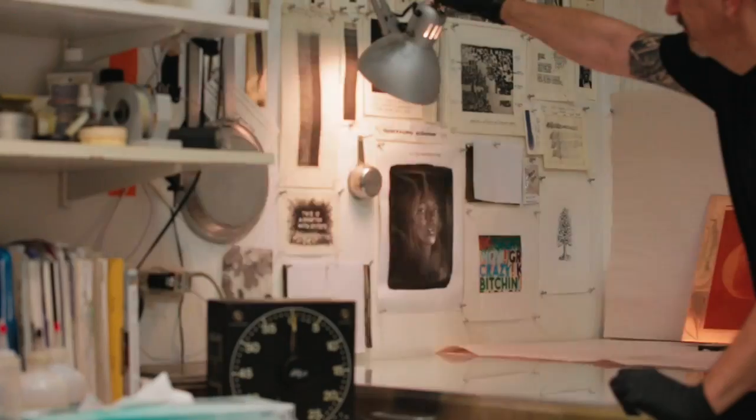We peel the paper off, and then we wash away all the soluble gelatin that wasn't exposed by the ultraviolet light. What this leaves us with is a gelatin stencil in negative of the photopositive image. We dry that then overnight, usually, but at least 6 to 8 hours. And then we stop out the edges of the copper with an acid resist, usually a varnish.